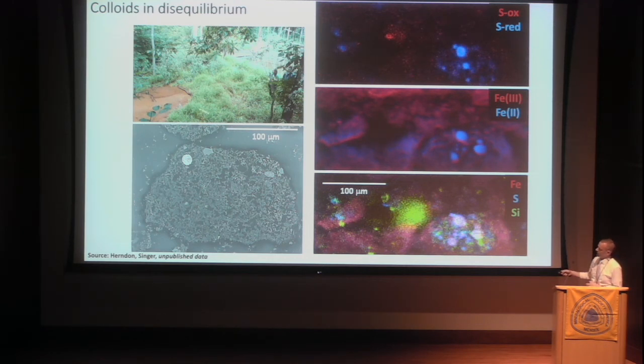Sampling colloids and suspended particles in here, we can see these large aggregates that are a mixture of, you can see this really beautiful framboidal pyrite, and a mixture of iron oxides, organic matter, silicates, and alumina, and secondary minerals as well. And this is pyrite surrounded by iron oxides, indicating just how in disequilibrium these particles are that are transporting materials over a long distance. And we can use X-ray fluorescence mapping and doing redox mapping to map out sulfur in different oxidation states, saying something about the iron redox state distribution, including the formation of oxidized rim on these particles, and linking that to the broader mineralogy.